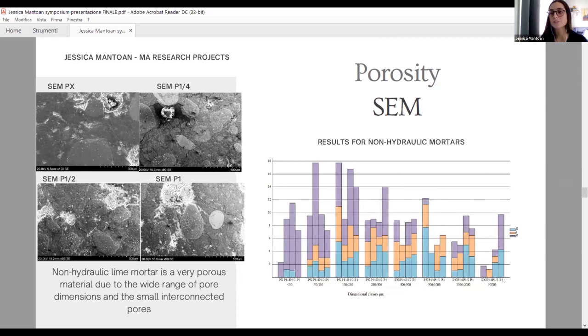That is a really strange result, considering that those kinds of pores are strictly involved in the density of the mortar. That means that our mortar containing a large quantity of barium hydroxide will be much less dense compared with the same mortar without barium hydroxide. And in a way, that can also explain the really strange result that we had for mortar containing a large quantity of barium hydroxide related to hardness, where the mortar was so soft that it was impossible to be measured.